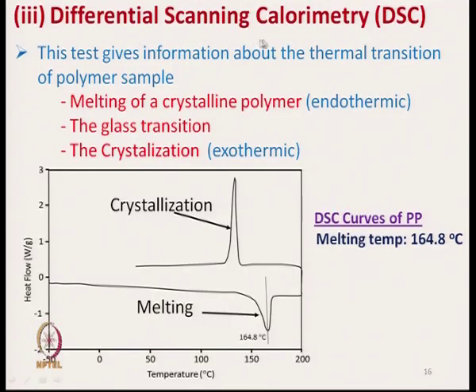Melting point is actually measured by the DSC method, differential scanning calorimetry. This test gives information about the thermal transition of the polymer sample. Thermal transition means that at a certain point it will absorb heat or release it. During melting it is an endothermic reaction, that is, it will take in heat. And during crystallization, which is exothermic, it will release heat, and you can also measure the glass transition temperature.